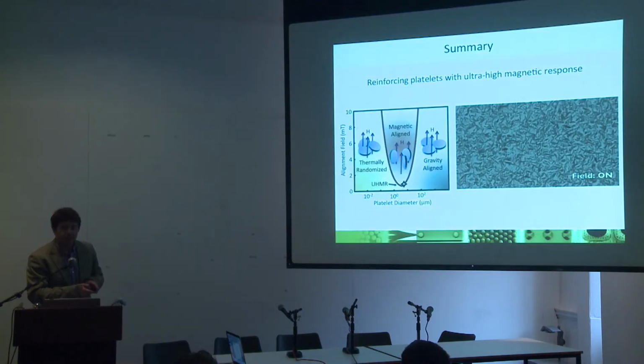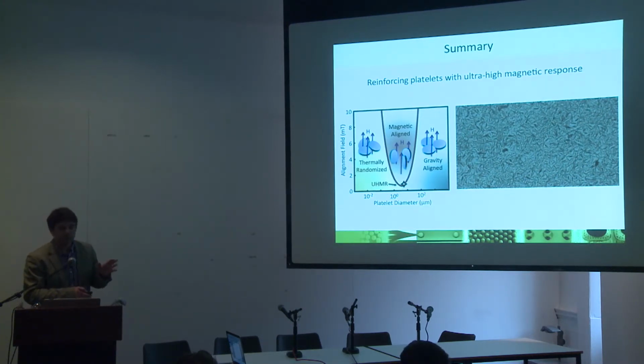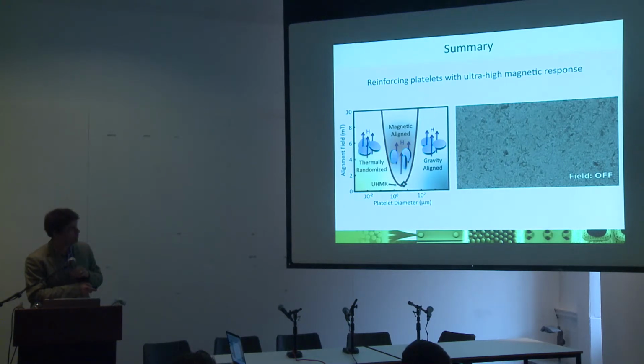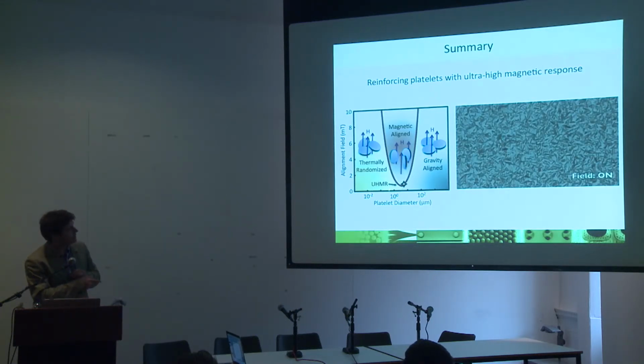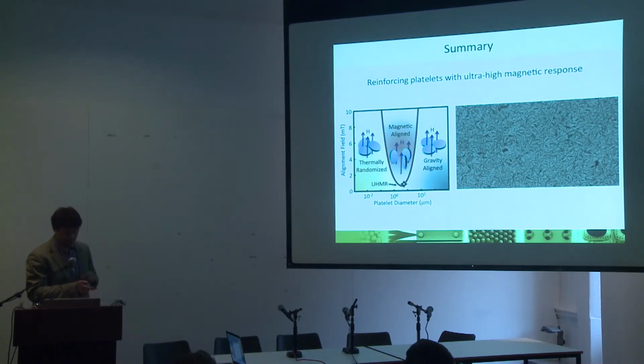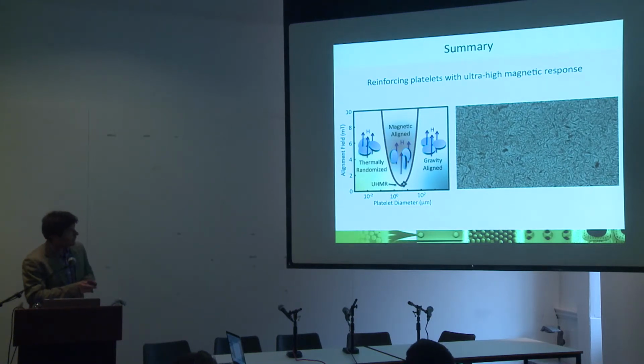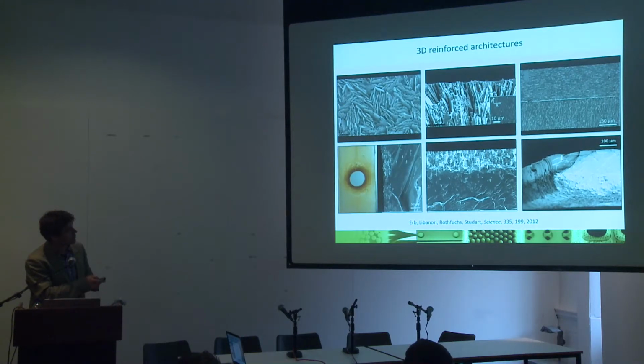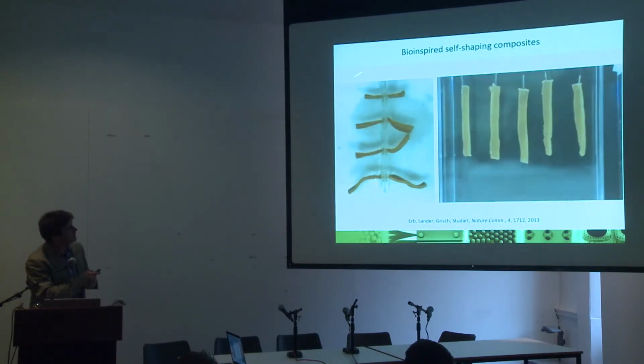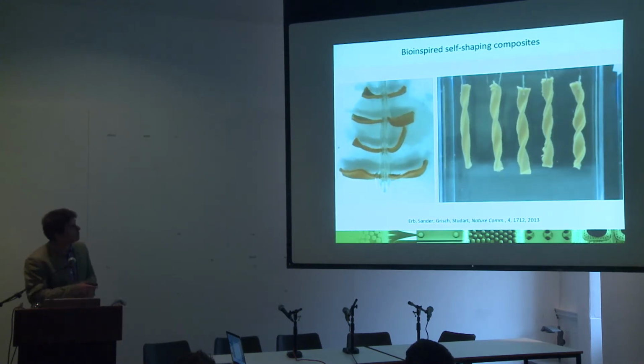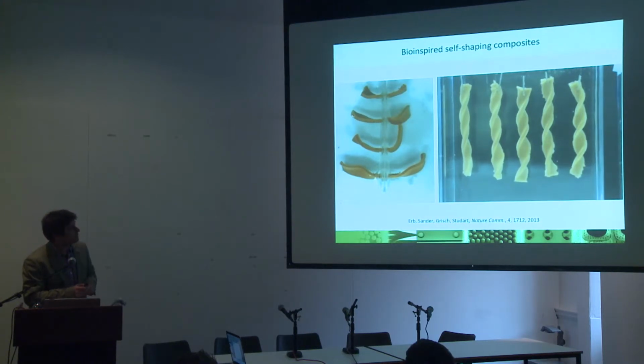So this brings me to the summary. I told you about technology that we've developed where we use magnetic fields in order to control the orientation of reinforcing particles, first in a fluid. And we had this surprising observation that it's extremely easy to align these particles as long as you choose particles with the right size. And then I told you about how one can exploit this to make a wide range of different microstructures that are not possible with today's long fiber composite technologies. And then I gave this example where we've used this ability to align platelets in order to achieve such a self-shaping effect, which can be bending, pure twisting, and combinations of the two.